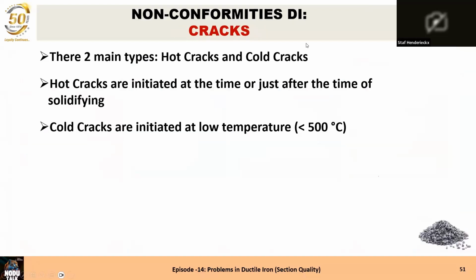So cracks, you have the hot crack and the cold crack. What's the difference? The hot crack is initiated at the time or just after the time of solidifying. So it means it happens when the metal is solidifying but has not yet strength enough to hold the stress of shrinking, and then it can happen.